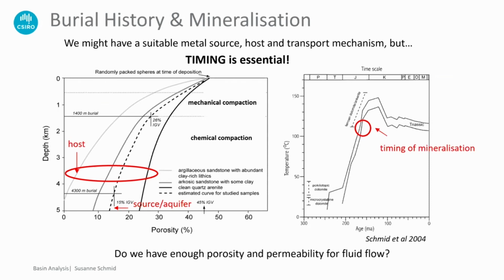So in this case, you see the source and aquifer in that example would look something like a depth of 5 kilometers, but your porosity is down to 15%. It's not that bad. And it also plays a role what diagenetic minerals you have. But the host is going down to quite low porosities and permeability. So you've got to look at both of those things in terms of seeing if you have a chance of mineralization to occur, of fluid flow to occur. And that's all assuming you have already identified your source of the metals and your fluid pathways and your structures that might have carried them.